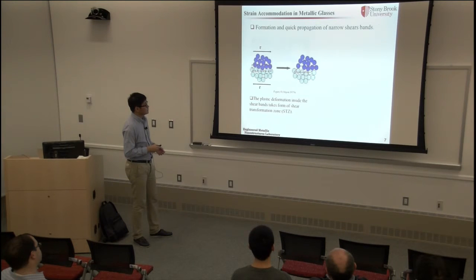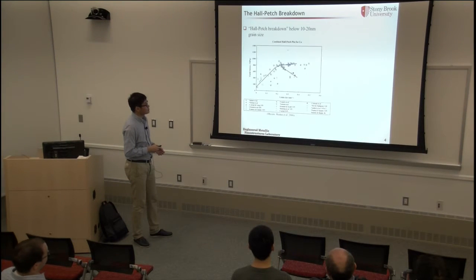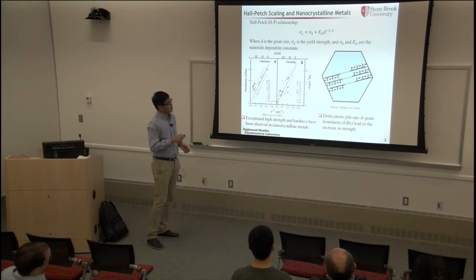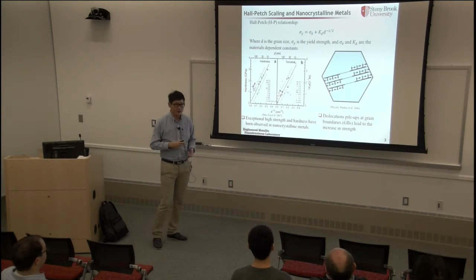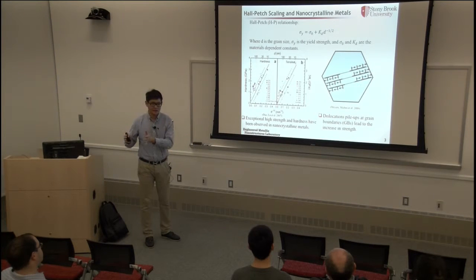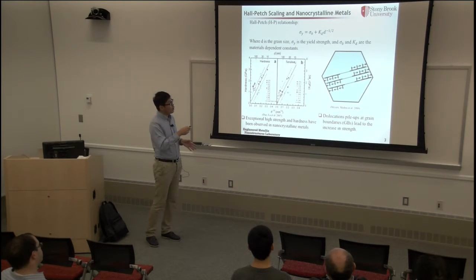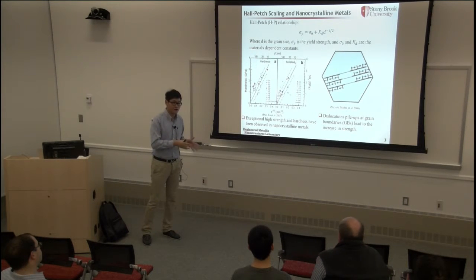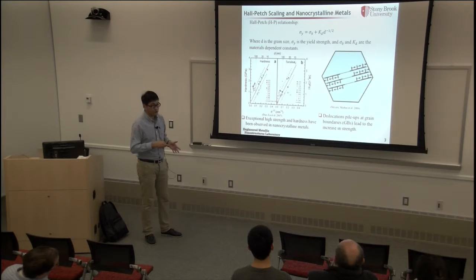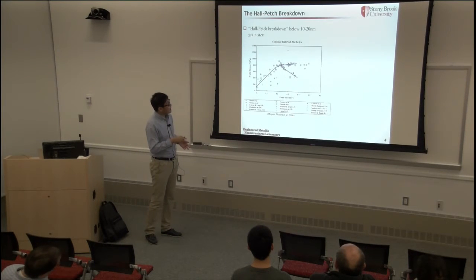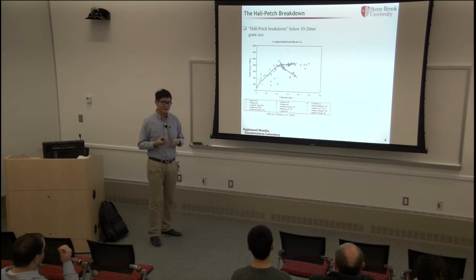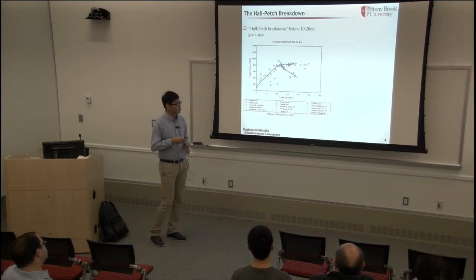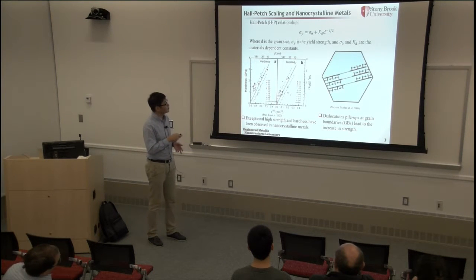So if we look at the first page, the Hall-Petch law, as it was developed, I think in the 1950s, we refine the grain size from the normal micron size to the ultrafine size, and this is effective, or true, from the micron size to the ultrafine size. The deviation from Hall-Petch only breaks down after the grain size is smaller than 10 to 20 nanometers. So I think the conclusion for the micron size is that the strength of the material still follows this Hall-Petch relationship.